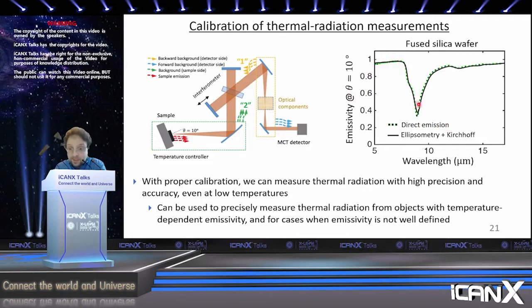And you have this green curve over here. And then the black curve is where we did some ellipsometry measurements on this wafer. It was flat, so we were able to do very good spectroscopic ellipsometry measurements and apply Kirchhoff's law. And you can see that these two curves fall exactly on top of each other. So we have very, very high precision and accuracy, even at relatively low temperatures. We can get this kind of agreement down to something like 30 degrees Celsius for our emitter, which we were very, very happy with.